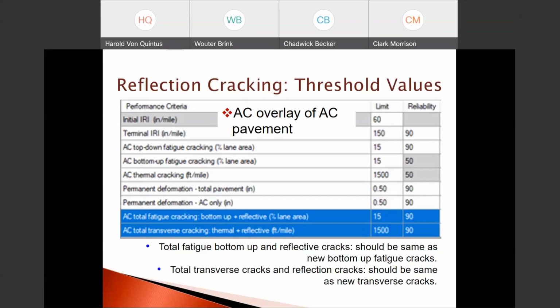It's generally recommended that the same threshold value be used for new AC bottom-up fatigue cracking and AC total fatigue cracking that would include new bottom-up cracks in the overlay and reflective fatigue cracks from the existing asphalt pavement itself. That is also true for transverse cracks, where the AC total transverse cracks, which includes new as well as reflective transverse cracks from the existing asphalt layer, that threshold be the same as new AC thermal cracking developing at the surface of the asphalt layers. It's generally recommended that those be the same threshold values.